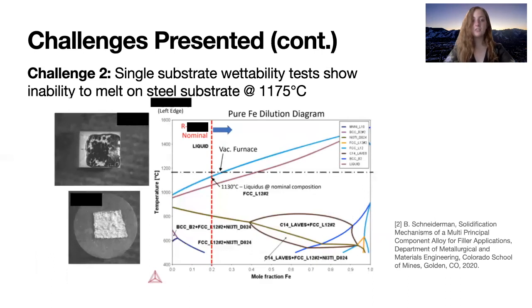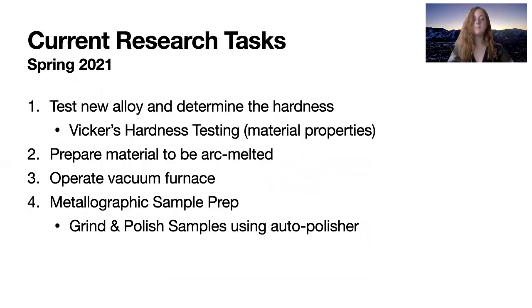And then the second challenge we're seeing right now is that we have a single substrate wettability test showing an inability to melt on a steel substrate at 1175 degrees Celsius. So we're looking to increase the temperature and see how that pans out for us.